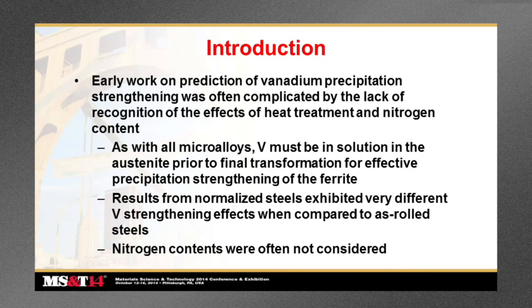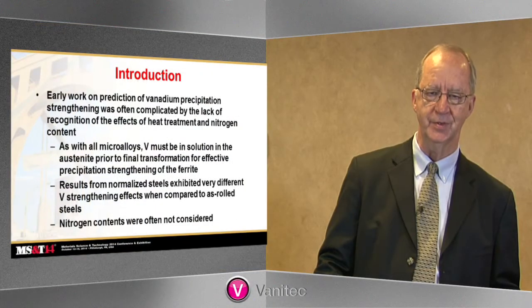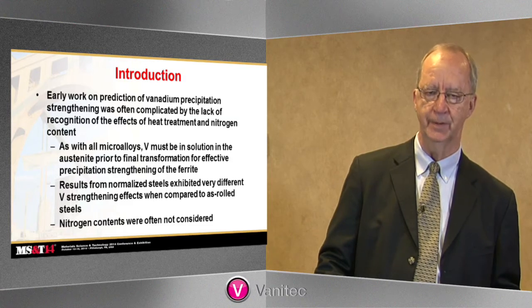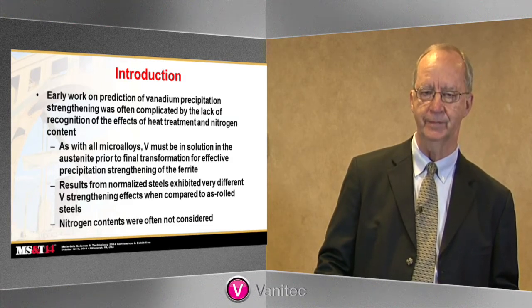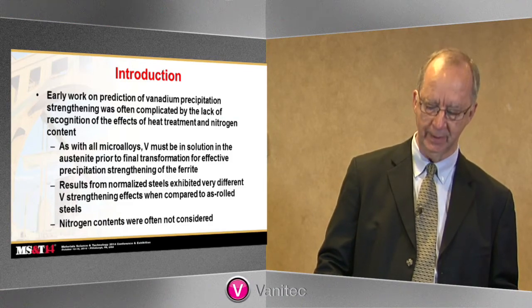Early work on prediction of vanadium precipitation strengthening was often complicated by the lack of recognition of the effects of heat treatment and nitrogen content. As with all microalloys, vanadium must be in solution in the austenite prior to transformation for effective precipitation strengthening of the ferrite. And results from normalized steels exhibited very different vanadium strengthening effects when compared to as-rolled steels, and often nitrogen contents were not considered. This resulted in some somewhat different perspective of what the strengthening effects of vanadium additions were, certainly some confusion and misinterpretation of data that was available.